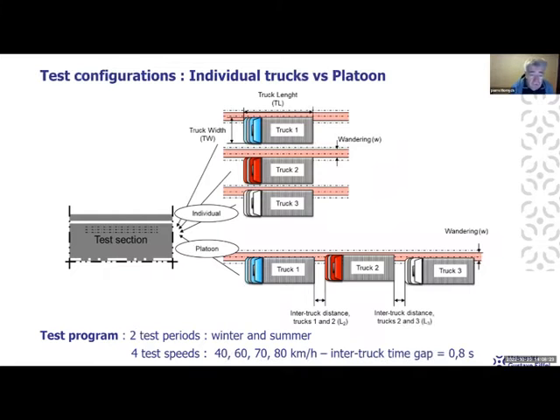And so the idea of the test was, we had 3 trucks, and the idea was to compare the effect of passages of a single truck and effects of the passages of a platoon. And because asphalt pavements are very sensitive to temperature, we did the tests at 2 different periods, in the winter and in the summer. And in each test campaign, we had different vehicle speeds. We had a lot of passes at 4 different speeds: 40, 60, 70, and 80 kilometers per hour. But we kept only one inter-truck time gap or distance, which was a time gap of 0.8 seconds.